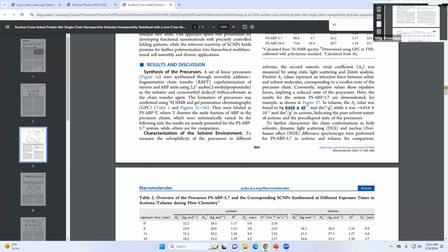And you notice the units. It should be volume, right? Or volume per mole. If it's B2, it should have units of volume because B2 is like the excluded volume. Right, so it could be molar volume, so dm cubed per mole would be the units. So this A2, if you multiply it by grams per mole squared, you end up with decimeters cubed per mole, which would be the B2 that we had before, just for context.